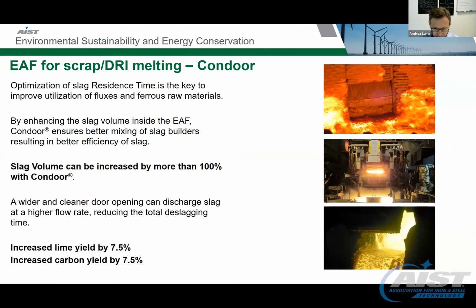Third point, which is, as I mentioned before, a little bit more process relevant, is utilization of what we call a slag valve. So far, in a conventional furnace melting DRI, you start the slagging after 10-15 minutes, and you keep the slagging for 20 minutes. Okay? So there is quite a lot of waste of energy. You cannot keep the slag inside the furnace, giving the right time for all the elements like carbon or lime to react in proper time.